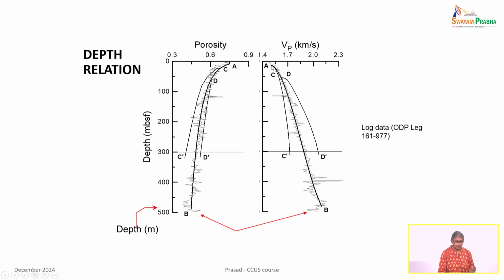that's seawater, about. And then as you go deeper there is a compaction trend, you can see it over here. Your porosity is reducing, it's almost 75% porosity. This is suspension, it's mostly mud. And as you go further and further down, your porosity decreases to about 35% at a depth of 500 meters. Corresponding to that, you have a change in velocity.